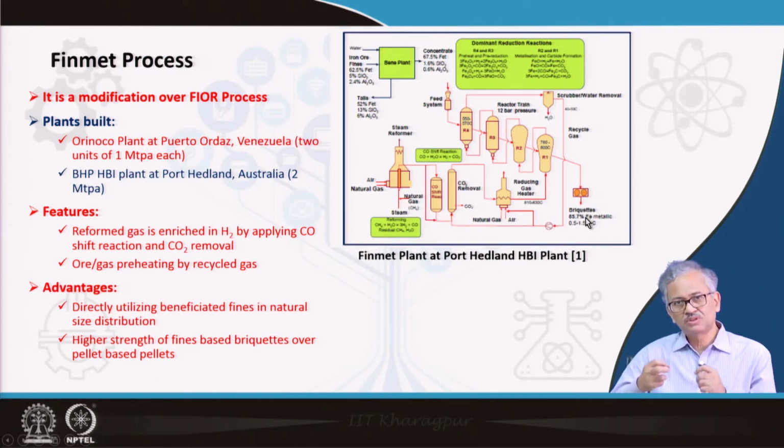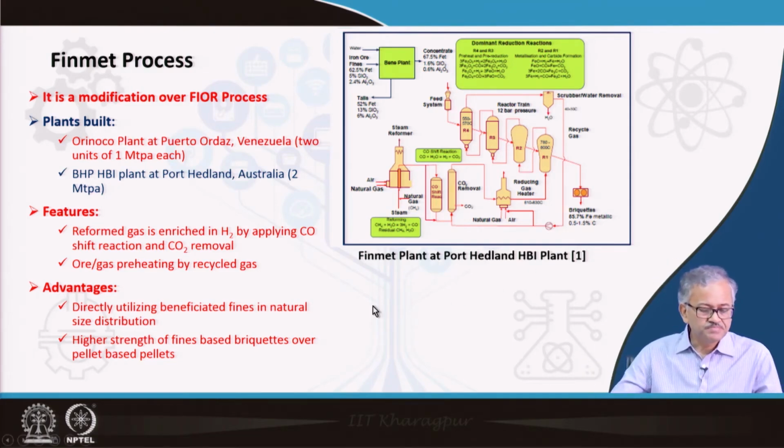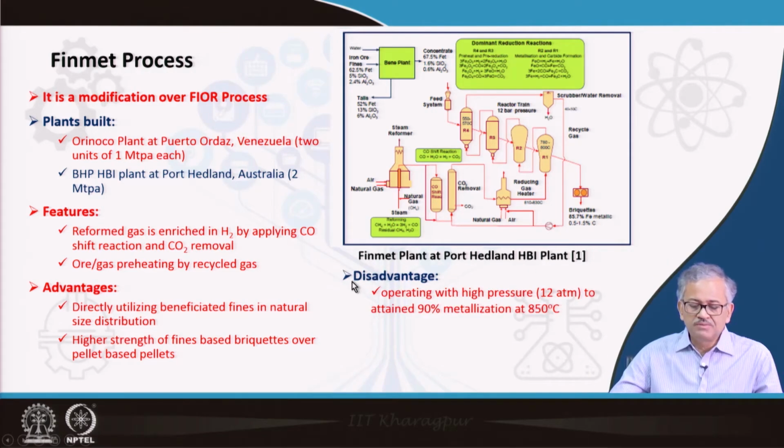Also, higher strength of the fine based briquettes over the pellet based, because the briquette is made from fines, and the strength of the briquette becomes higher than if you briquette pellets. So fine based briquettes are much stronger, so you can transport them to a longer distance.